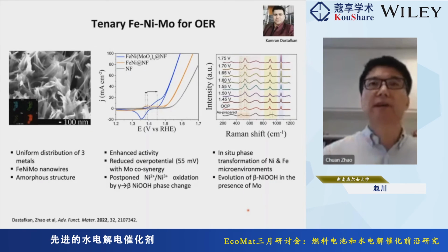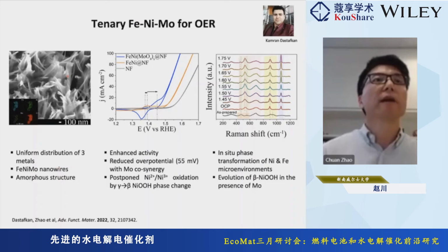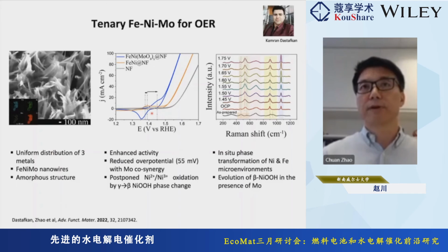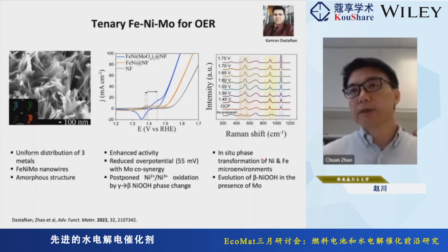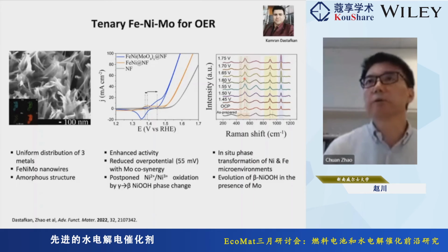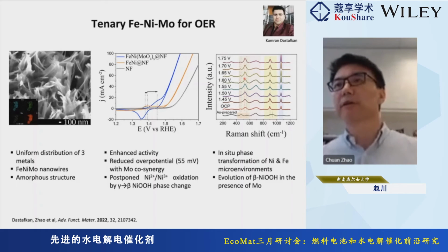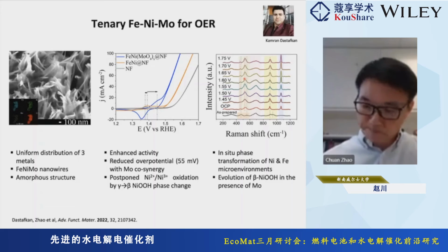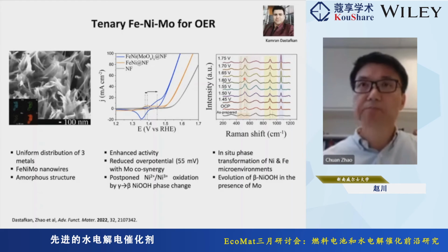We further extend this concept to other metals. For example, in this study, we extend that into nickel, iron, molybdenum for OER, and we can form this amorphous nanowire structure. And we also observe the improved OER performance as well as the shift of the pre-oxidation peak of nickel. Again, the operando Raman suggests clearly the beta phase nickel oxyhydroxide is the dominant phase when using this catalyst for OER.